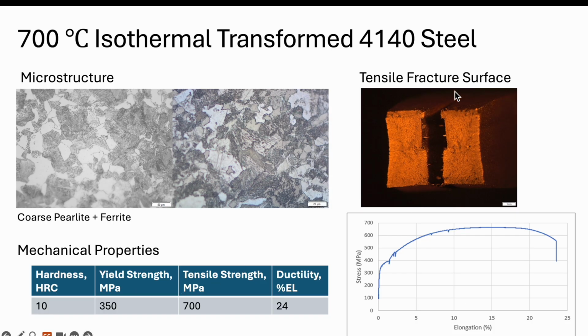And again, our tensile fracture surface is kind of not exactly rectangular because of the plastic deformation. This is not very flat from that ductile fracture, so we're not seeing as much of the brittle, and so this is less and less flat as we go along in these structures.